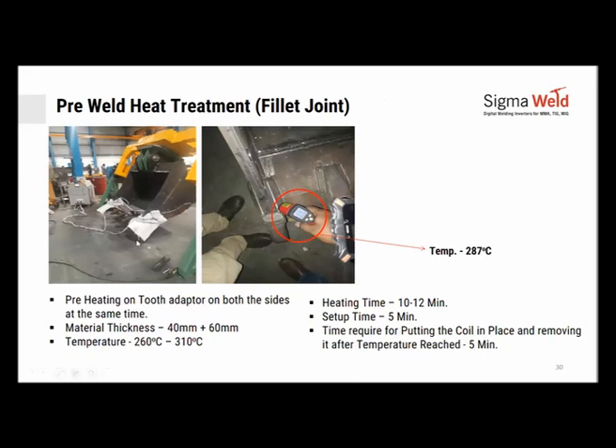When they are welding the corner teeth, they need to preheat both of them at the same time to avoid distortion, and welding also happens parallelly. To do that, the same equipment, the one coil has been made, split it, the second coil has been wound here and goes back to the equipment. Both the joints have same thickness, same geometry, 40 plus 60 mm. We were able to achieve the temperature of 310 degrees in about 10 to 12 minutes.